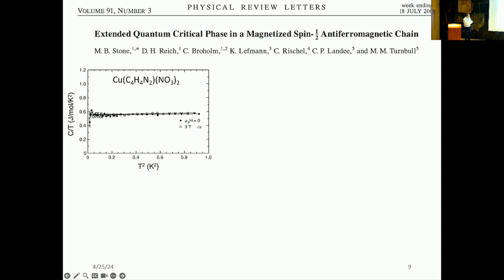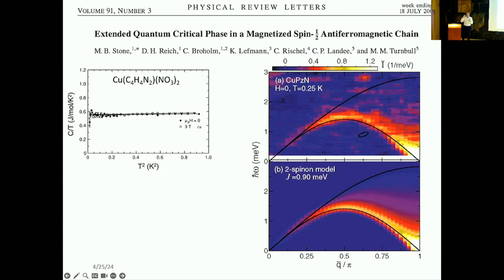And here's shown a really curious measurement of the ratio of specific heat to temperature versus temperature. And you'll see that in the limit of very low temperatures, there's a Sommerfeld constant in this material. So you know this from metals. In metals, because of the presence of the Fermi surface, there's actually a finite limit to C over T when you go to low temperatures. This material is actually an insulator, and yet it still has a Sommerfeld constant. So that's a very weird thing, which actually is a result of having forced the magnetism down to one dimension, where there can be no phase transition, and instead you end up with a one-dimensional Fermi liquid forming itself in the chain.